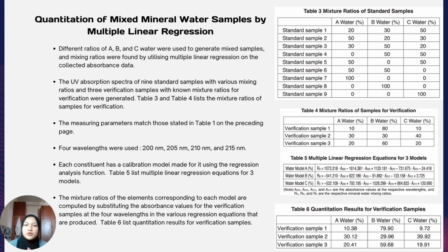Lastly, the mixture ratios of the elements corresponding to each model are computed by substituting the absorbance values for the verification samples at 4 wavelengths into the regression equations that were produced. Table 6 shows the quantitation results for verification samples for each water: A water, B water, and C water, and for each verification sample. And the result shows positive results.